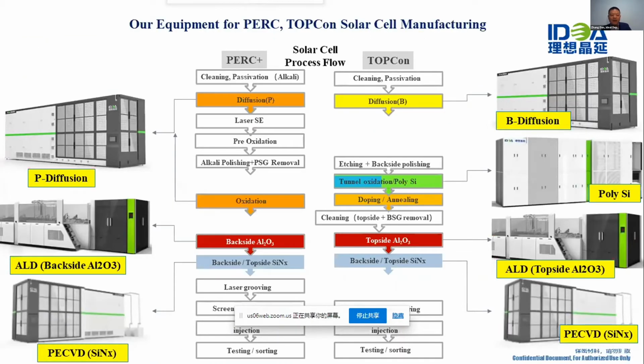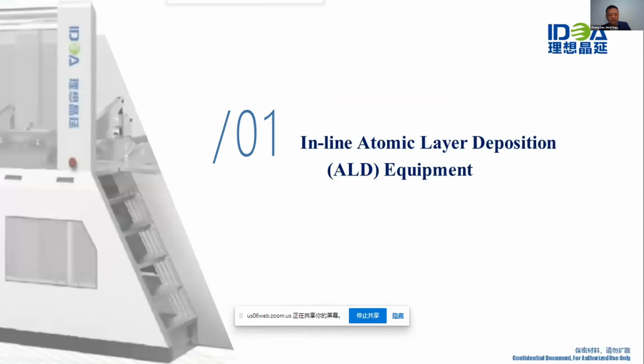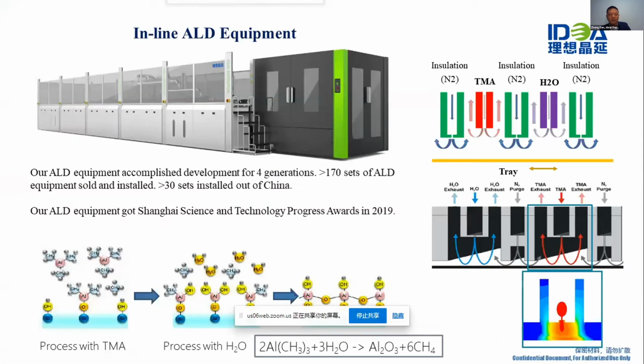Here is our equipment portfolio for the solar business. For PERC and TOPCon solar cell production, we provide diffusion equipment for both phosphorus diffusion and boron diffusion. We also make inline ALD equipment for aluminum oxide deposition. We built PECVD for silicon nitride deposition and polysilicon for the TOPCon process. From 2015, we built China's first inline ALD equipment. We have developed 4 generations of ALD equipment, and our ALD equipment got the Shanghai Science and Technology Progress Award in 2019.